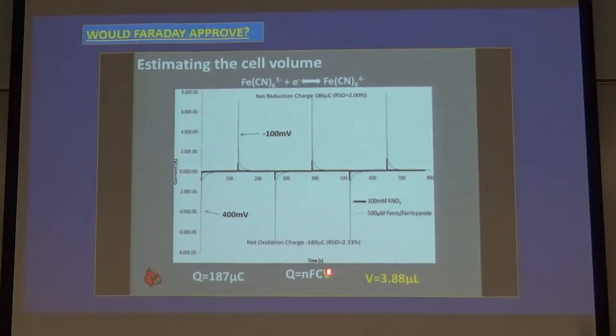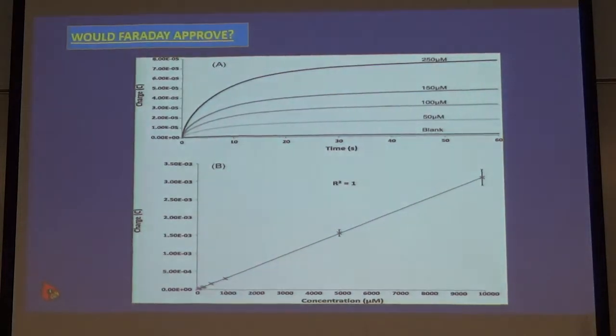We can do an experiment like that and use it to calculate the volume of the cell. So this cell is about 4 microliters. Is this good electrolysis? Would Michael Faraday like it? Well, if we do this experiment for solutions containing different ferrocyanide concentrations, and we plot the charge that's accumulating over time, this goes out to a minute. The blank doesn't give us much of anything, but as we increase the ferrocyanide concentration, the charge that we accumulate builds up. It's a nice linear relationship. So far, so good.